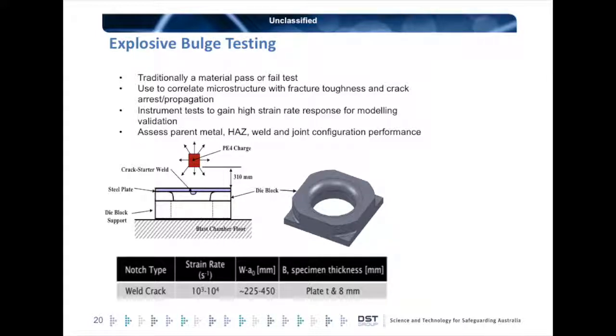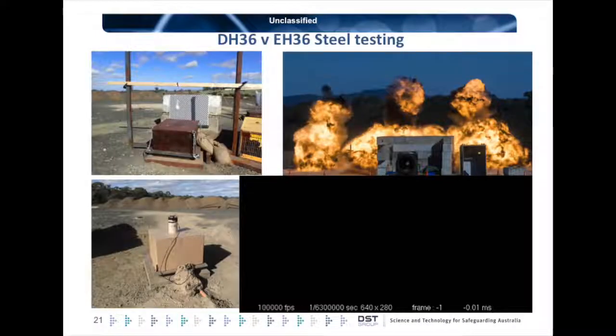on platforms. We've also worked on a variation of this test in terms of changing the explosive charge size, moving it different distances away, and that's been part of our high strain rate explosive testing. From that we're trying to get the specimens to deform at different rates, and trying to capture that information with sensors. And in the next slide, this video may or may not work, but this is a section of hull plating here, sitting on top of the die block.